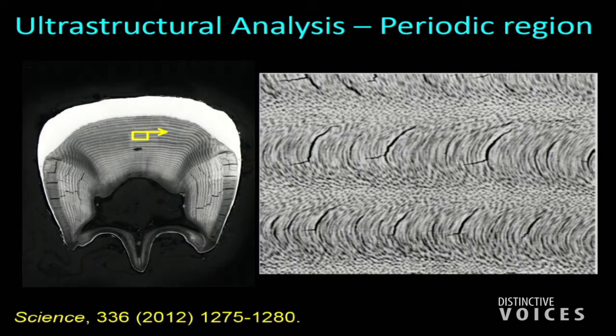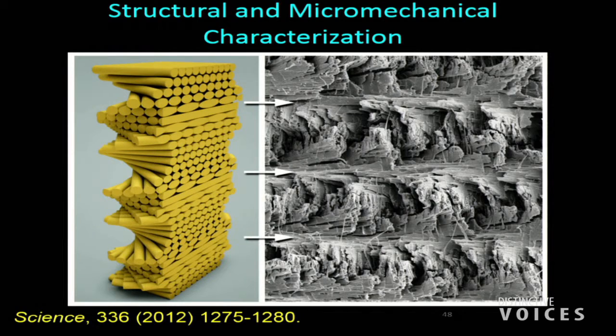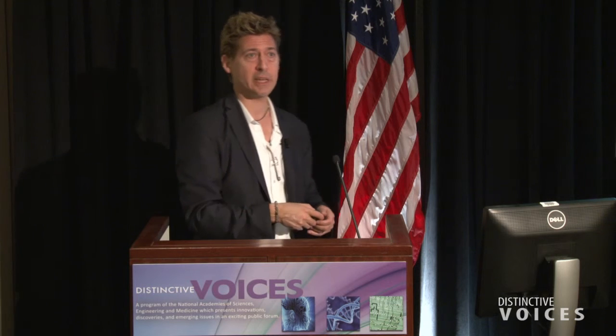Okay, so this is what we find is one of the most exciting regions of the club, this interior, which we call the periodic region. So when we first analyzed this club, we polished it flat. We noticed all these cracks, and these cracks have this C pattern to them. What's going on? Where are cracks forming, and where do they go? So we fractured open the club, and when we did in this region here, we see this structure. This structure is called a Bouligand structure or a helicoid.